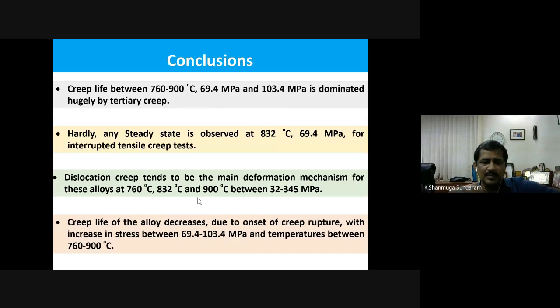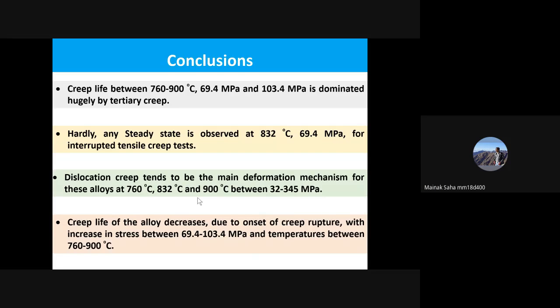Why do you always restrict between 69.4 and 103.4 megapascals when you could have the dislocation creep between 32 to 345 megapascals? Yeah, okay. So definitely, within that 32 to 345, this has been taken from the earlier literature. The literature I mentioned says that the dislocation creep can be observed there. But for 69.4 and 103.4, they have provided a list of the activation energies, as well as the other data, like the creep rupture data, the stress exponents and all.